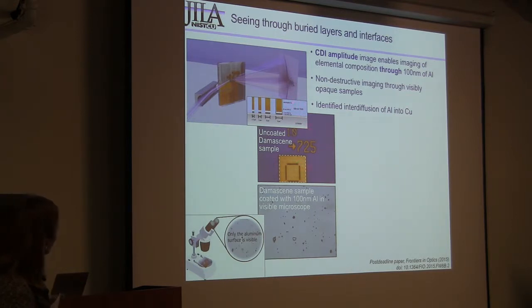And so we took that sample, and they didn't need us to keep it clean, so we put it into our very dirty coating chamber and coated it with 100 nanometers of aluminum. So if you look with a visible microscope, you just see a mirror.